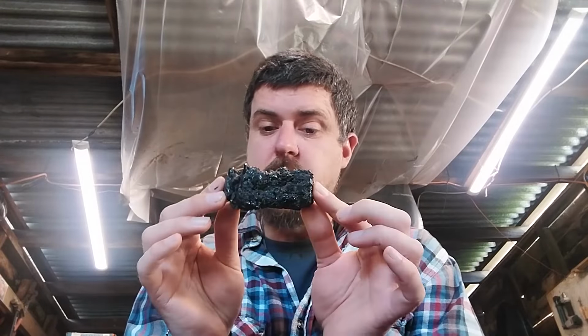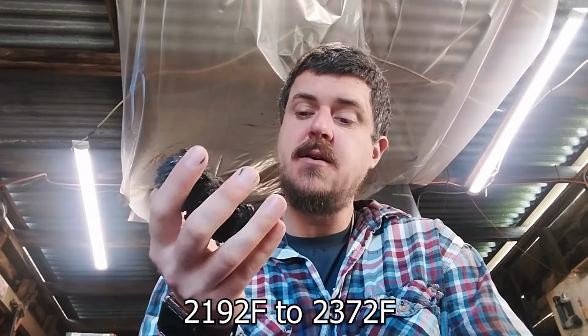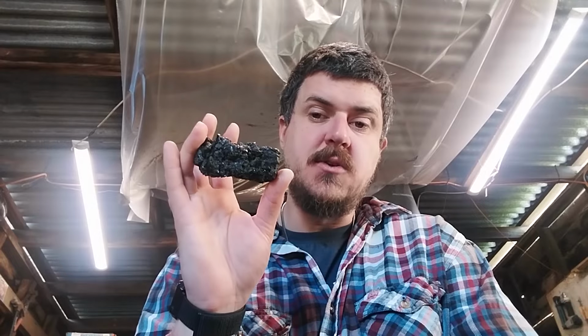I'm trying to close up as many of the voids as possible. I'm trying to get my surface finish as nice as possible. And I'm going to be doing it all at forge welding heat. I'm going to use my infrared thermometer, and I'm going to make sure that I'm sitting at around 1200 to 1300 degrees on this. And that's the only temperature that's really going to be valid to work this. As soon as it starts getting down towards the reds or into a dull orange, I'm not going to be doing much other than changing surface finish. So I want to reflux it, get it back in the forge, and do this over and over and over again. So I will know when it's done because every direction that I could possibly forge on it, it will feel solid, and then it'll be time to wrought. So let's get this consolidated first, and you can see it happen.